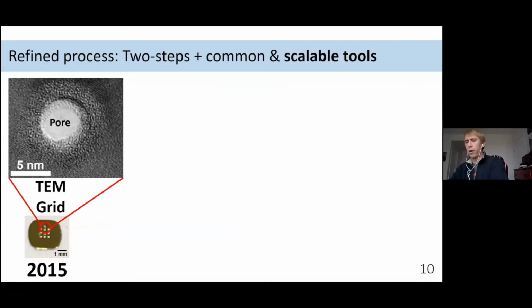And so the other important piece here is that we were able to scale up. Obviously when we started this process, we started working on a very small scale, in this case back in 2015 on a TEM grid, for instance. We can see here that we were indeed able to confirm the very first question was, can we make these very small pores in this intrinsically chemically and thermally durable material? We found out back in 2015 that we could do this, at least on the very small scale,